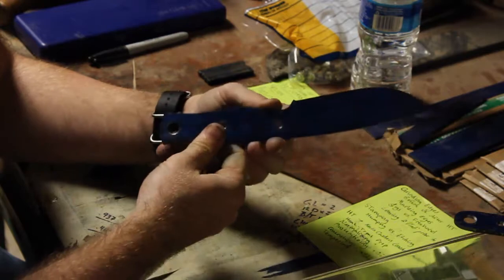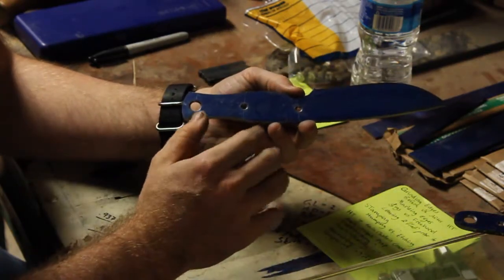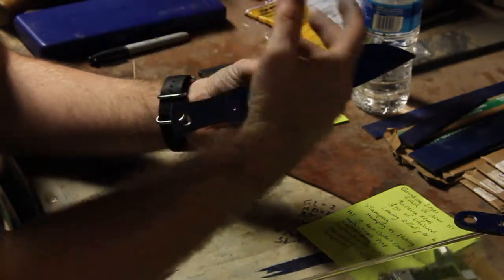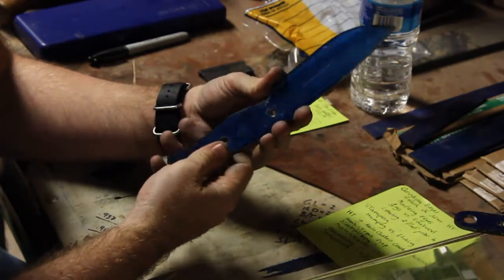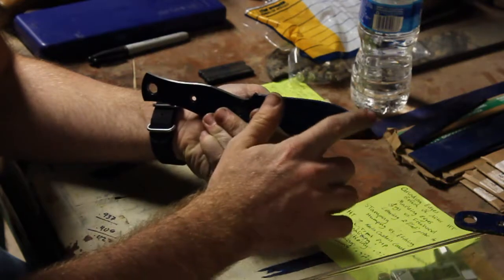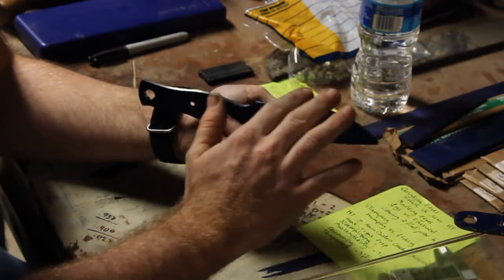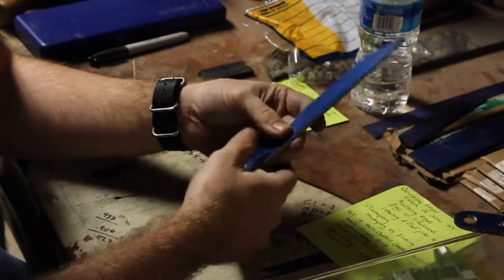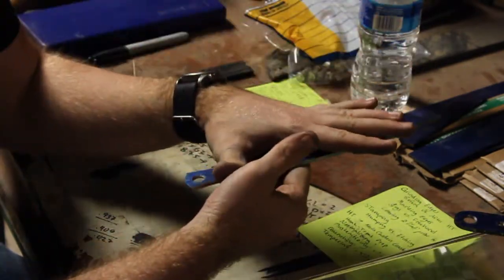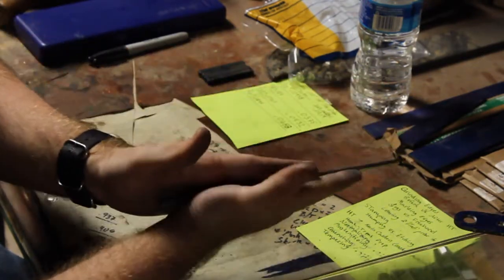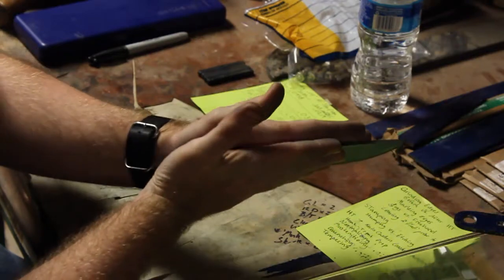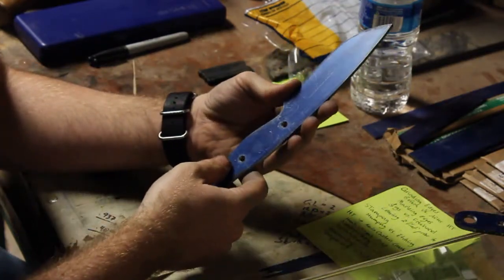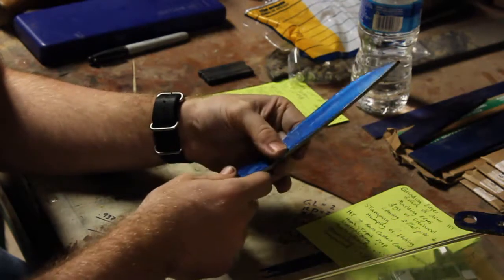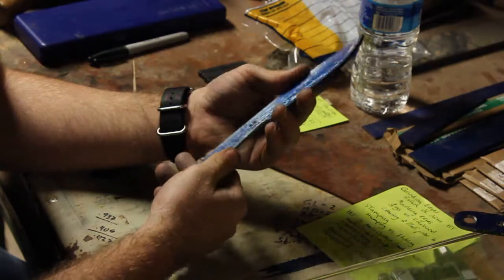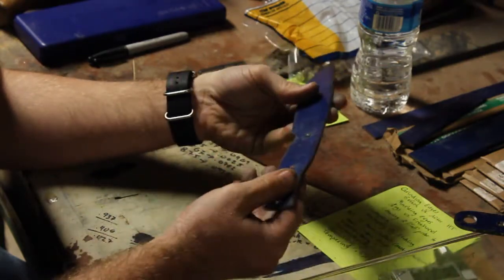And the reason for this is when you're forging, you're inducing different kinds of stress into the steel because it's being heated, hammered, and cooling off, dozens of times. When you're grinding knives out of stock, all of this up here is being exposed to more heat than maybe this back here, and it's important to redistribute the properties of the steel correctly, and to just kind of clean up the grain structure, which is really what you're striving to do when you normalize. Many times I'll triple normalize because it's good for the steel. Can't hurt it.